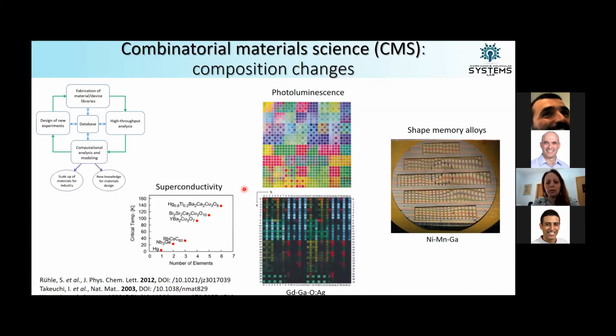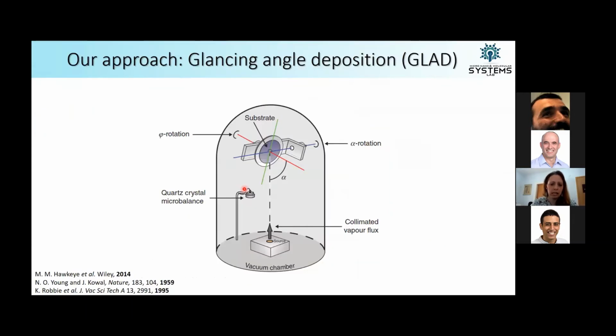What I wanted to do in this work was be able to combine this with one of our methods that we use at the Max Planck Institute, which is glancing angle deposition. I'll explain a little bit about it now. It's a PVD method where it can be done in a sputtering system or an E-beam system or any other PVD system. However, the main difference is that our substrate is not parallel to the source of your material. It's actually tilted at an angle called alpha, and these are very high angles, usually above 80 degrees, between 80 and 90 degrees. And you can tilt this angle and change it, and also change the rotation.